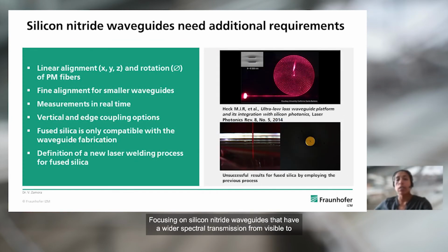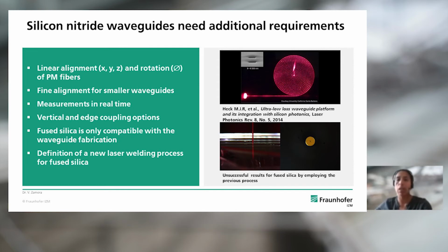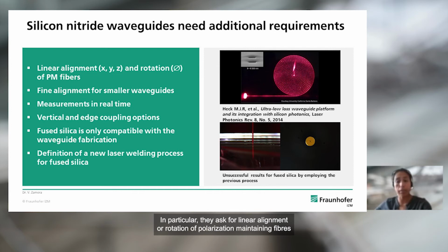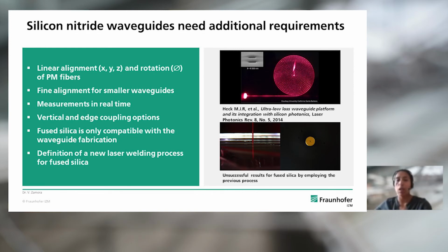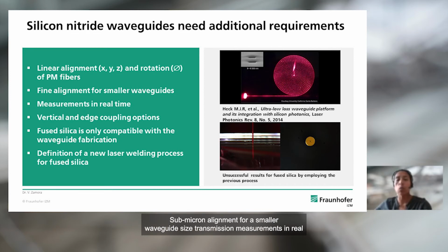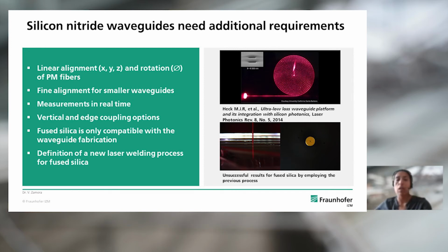Focusing on silicon nitride waveguides that have a wider spectral transmission from visible to mid-infrared, additional requirements are necessary for the successful implementation of the laser welding process. In particular, they ask for linear alignment or rotation of polarization maintaining fibers, PM fibers, because the waveguides show a polarization dependency. Submicron alignment for a smaller waveguide size. Transmission measurements in real time to carry out the welding process. Vertical and edge coupling options. The most important item is that fused silica glass is the only one compatible with the fabrication process of the waveguides.